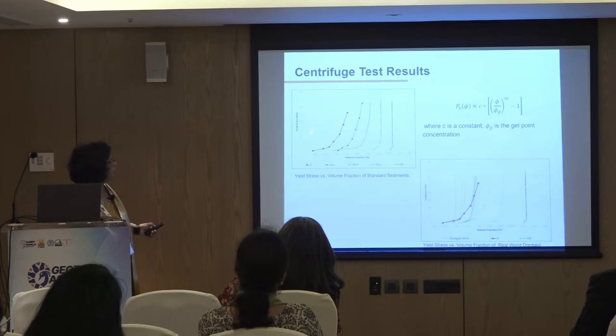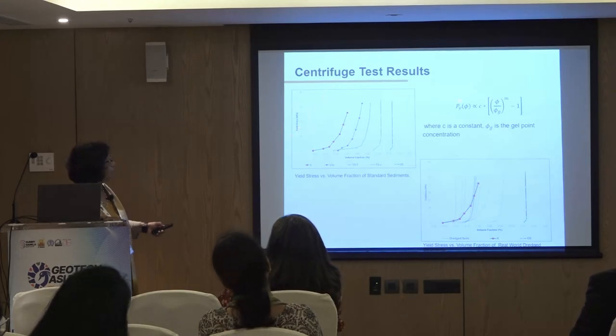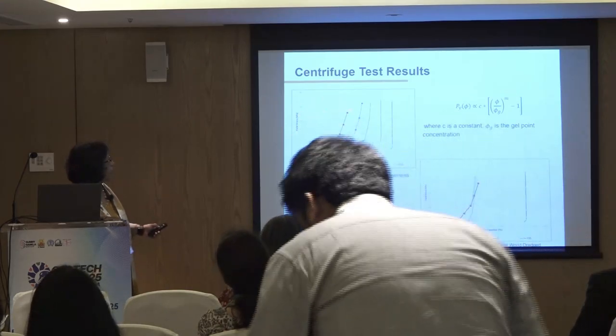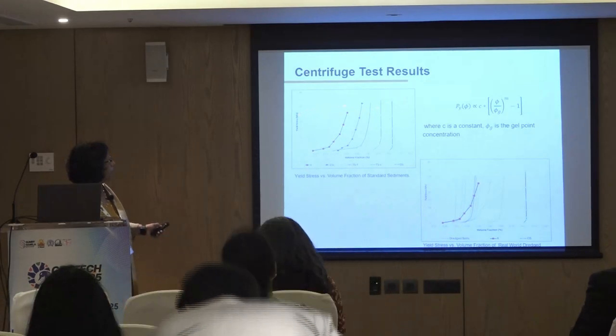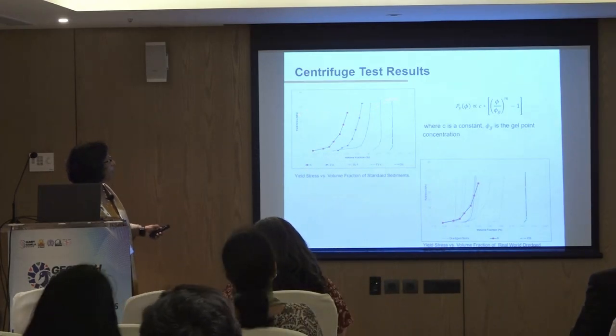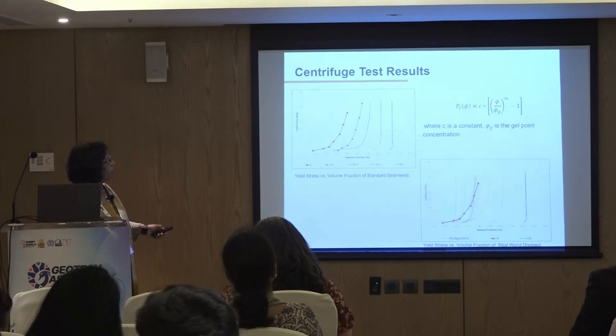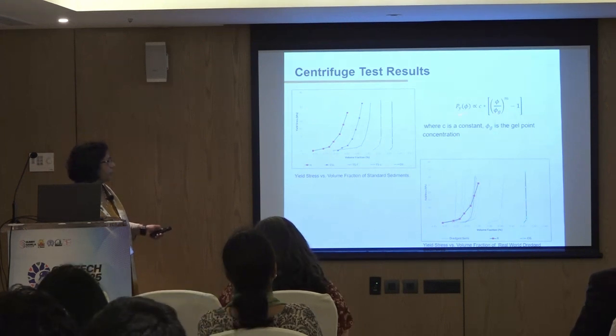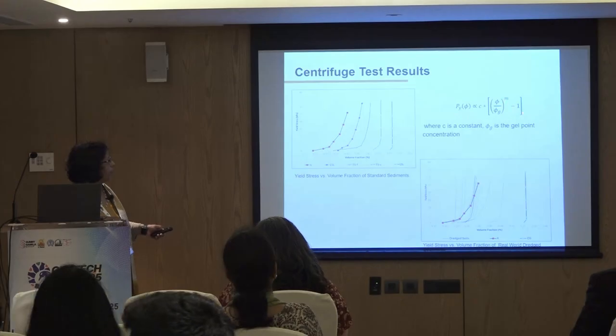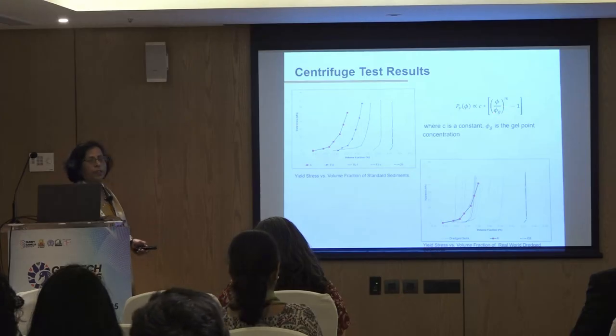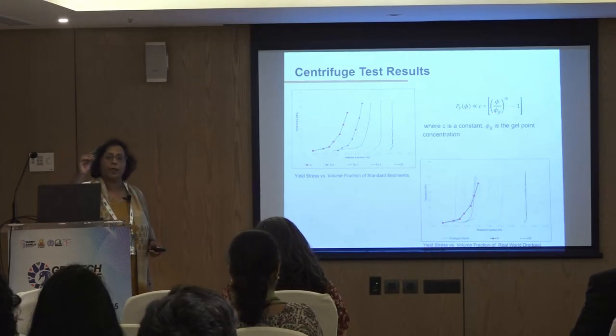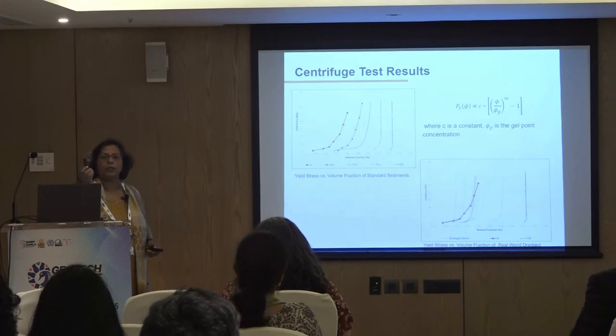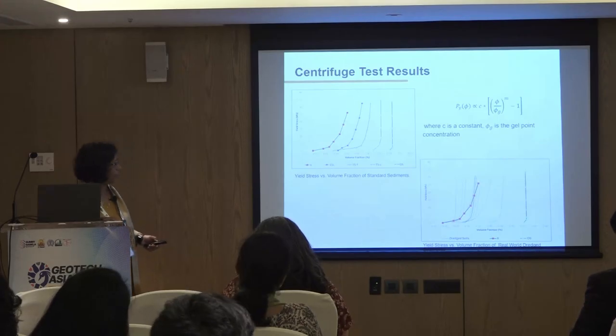And one thing that is important to see is what we call yield stress, which is Py. That gives you an idea of what the final solid content is. And you can relate this Py value to the percentage solid, and this is called a gel point. So I'll show you some data about gel point, and this is what industry needs in the field. When they bid for a project, and you get a slurry, they need to predict what solid content will be achieved in the field.